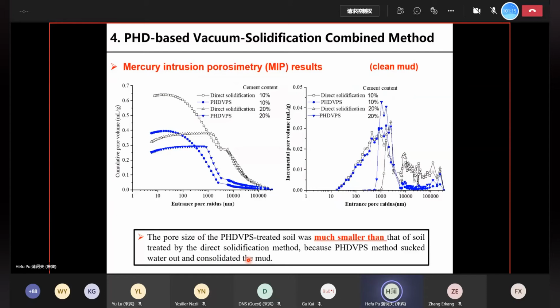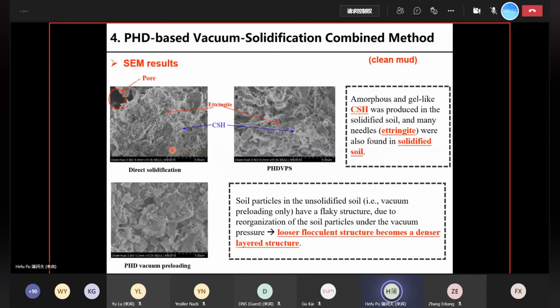We also look at the MIP test to look at the pore size distribution. Okay. I will accelerate. So you can see that after the treatment with the proposed PHDVPS method, the pore size was significantly reduced. We have fewer large pores and more small pores. That explains why we have significantly increased shear strength. This is the SEM results. I will skip this because of the time limit.